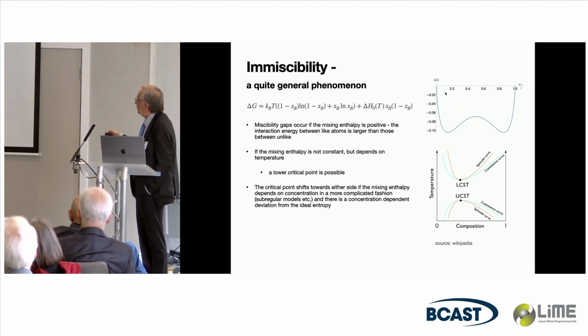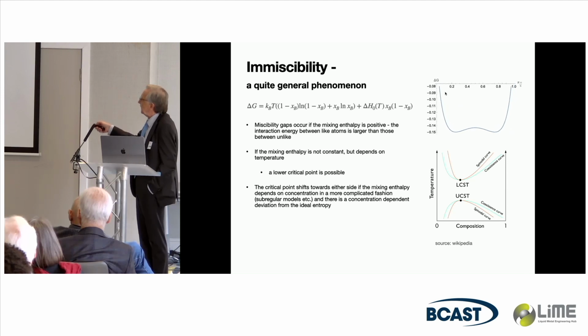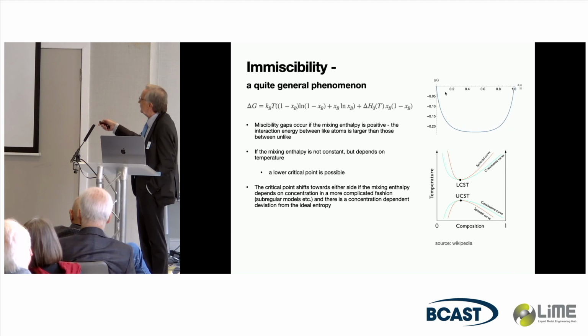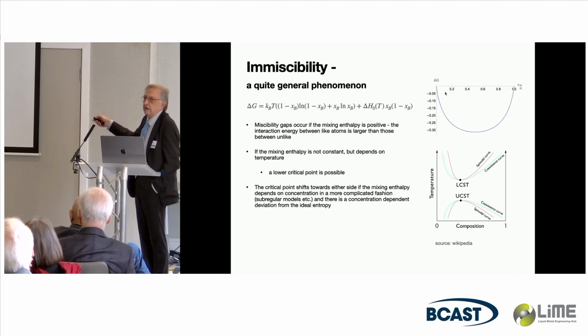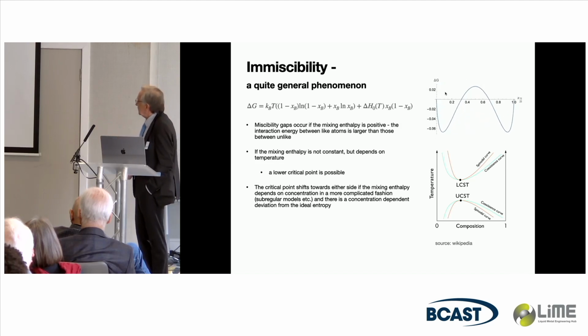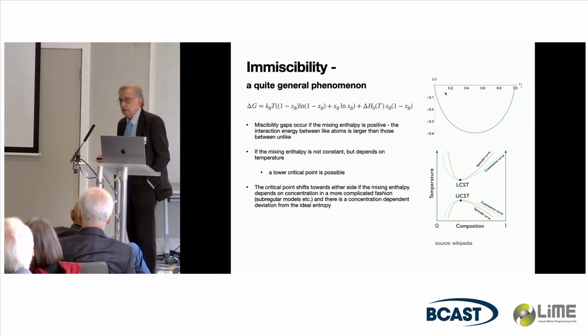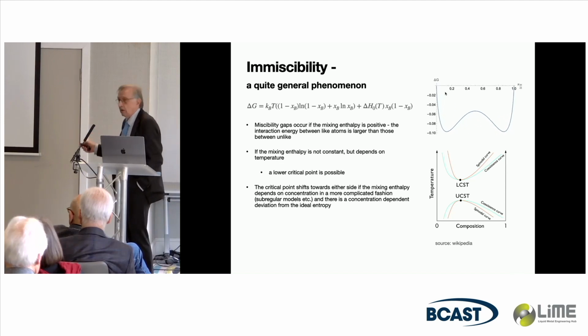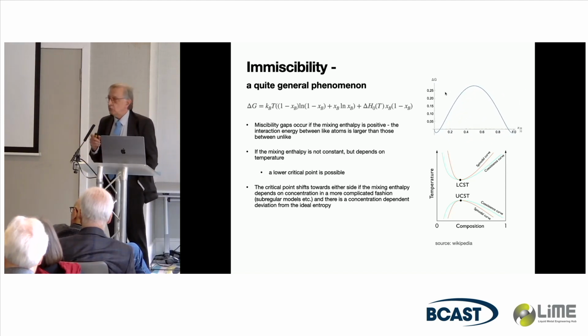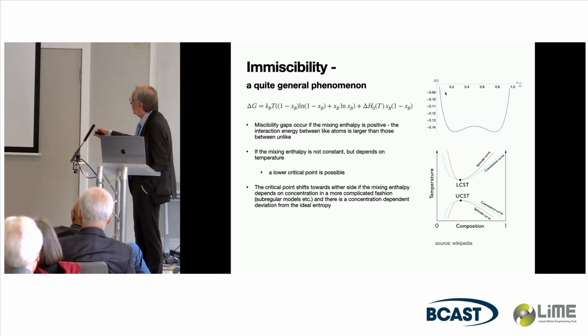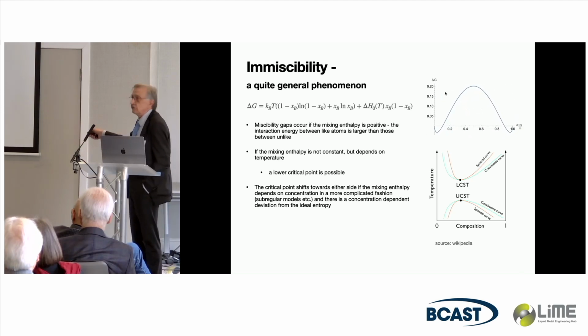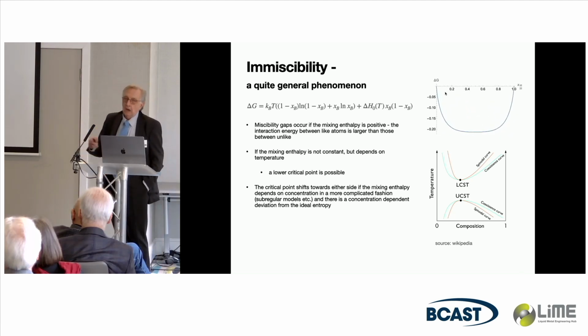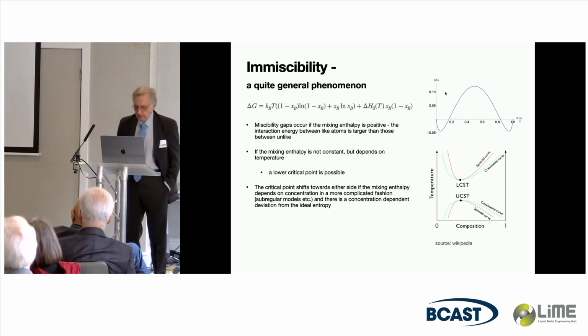And in reality, of course, everything is not that simple. In reality, the ideal entropy of mixing might depend on much more complex terms in concentration. And the enthalpy of mixing does not have this simple parabolic form, but has additional composition dependence. And let me make a remark: even in organic materials, you might have a closed loop. So this miscibility gap is closed in the temperature-composition range. It depends on how the molecules interact with each other.